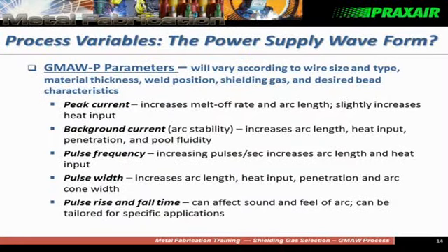For pulsed MIG welding, these are the characteristics you can control. The peak current, which is the maximum current that squeezes off the droplet; the background current that establishes the basic arc length and heat input of the system; the pulsing frequency, which relates to how many times that current level goes up to a high level and squeezes off a droplet; and some other characteristics of the pulse, how wide and how high. Again, the amount of energy you put into the system.